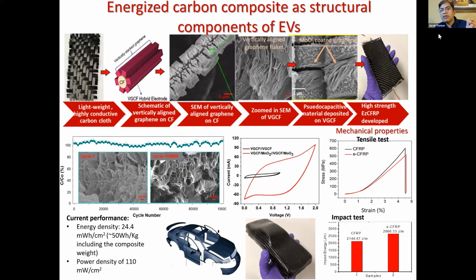And then we made that into a composite, and here you can see the mechanical properties of that composite compared to a commercially available CFRP, which is given here. And by making it into an energy storage device, the mechanical properties are still intact. That means the tensile strength is more than 80% of the commercially available carbon composite sample, and the impact energy is also similar to that of the carbon composite. And this can give a high energy density as well as high power density.